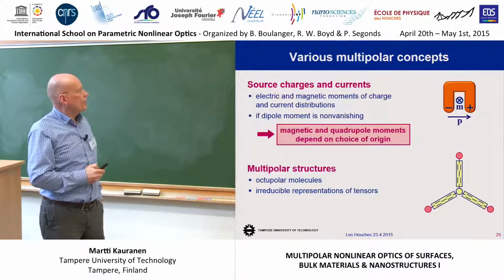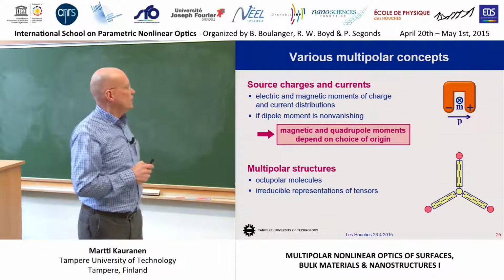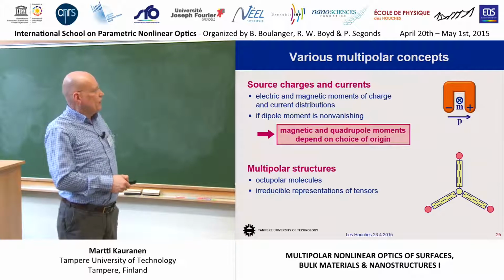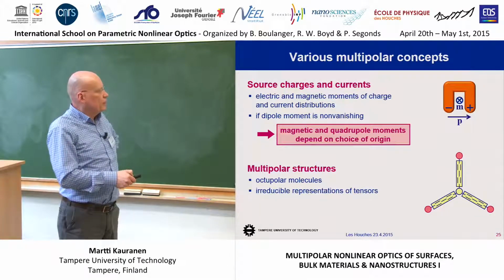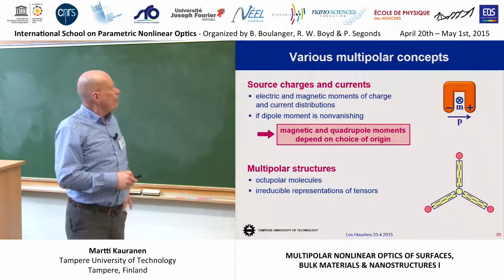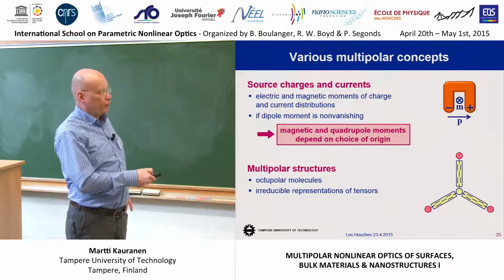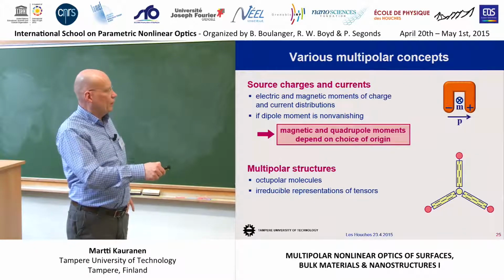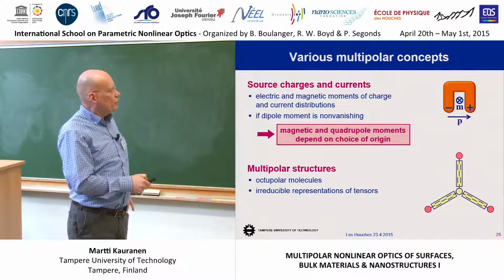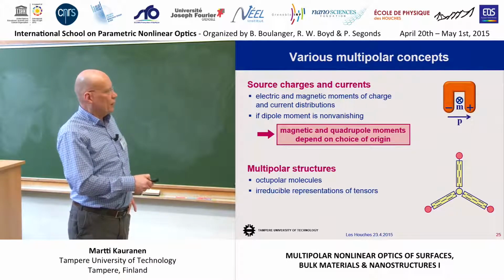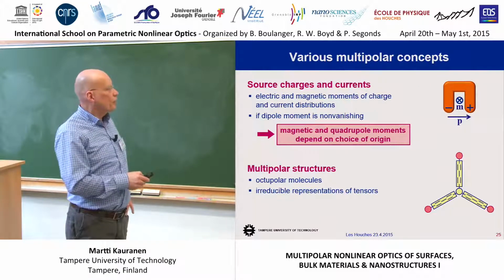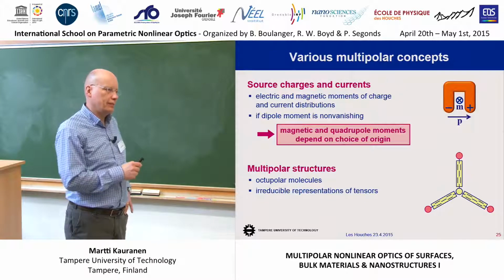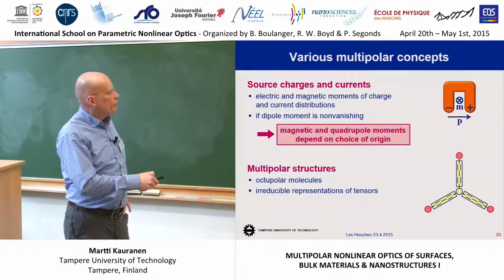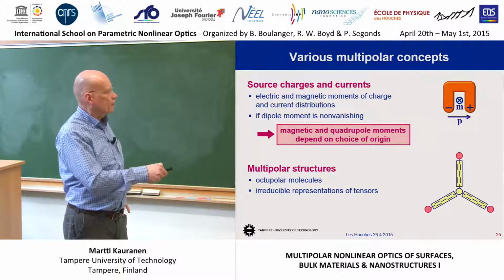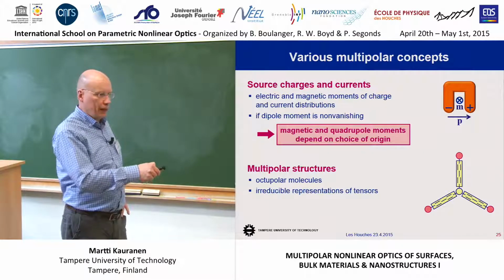Okay. Then another thing that I think is important to note in the context of metamaterials. This is one of the favorite structures for the metamaterials community, the split ring resonator. If you excite this using light which is polarized this way, then you can force the charge to oscillate along this path. So at some point, your charges might be at the ends of the whole structure, and then certainly you have a dipole moment here. Nevertheless, the community usually emphasizes the magnetic response of these structures. And sure enough, when the charge moves back and forth here, you have a nanoscale current, so you're going to have a magnetic moment that oscillates out of the plane here.